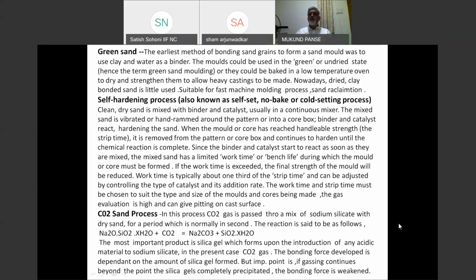The major disadvantage of this process is the gas generation and cost. The gas generation when the resin burns is substantially high, and that's why you get pitting from this gas when it is generated. You have to take proper care with applying proper coating and having sufficient permeability or venting of the mold so that the gas doesn't come inside the casting.